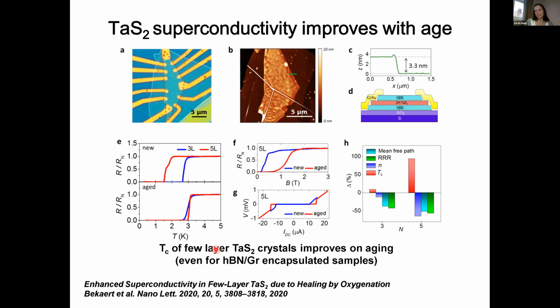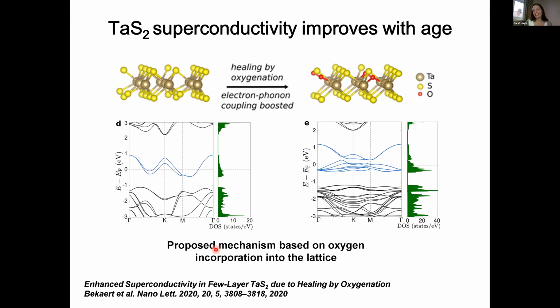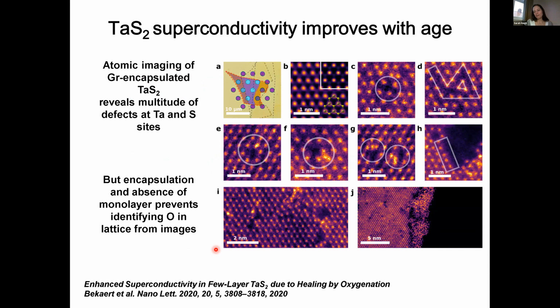At the same time, they asked the theory group in Antwerp, and they had come up with this principle that if you substitute oxygen into the tantalum disulfide lattice, a little bit like we'd already seen in the gallium selenide, you should be able to explain this improved superconductivity. So the question was, can you see the oxygen substituted into the lattice? Unfortunately, the difference between tantalum, oxygen, and sulfur means that it was not possible for us within the graphene encapsulated structures to distinguish between a sulfur vacancy or a sulfur site and an oxygen substituted sulfur vacancy.